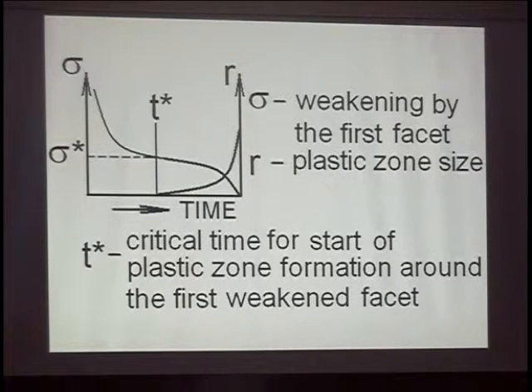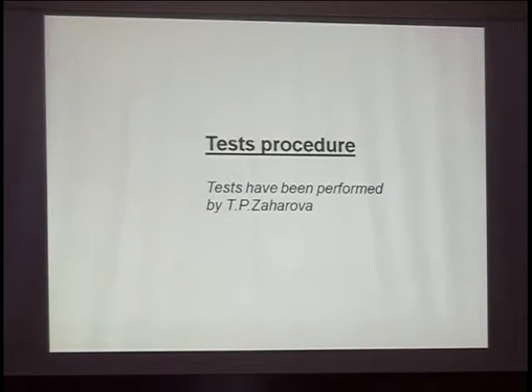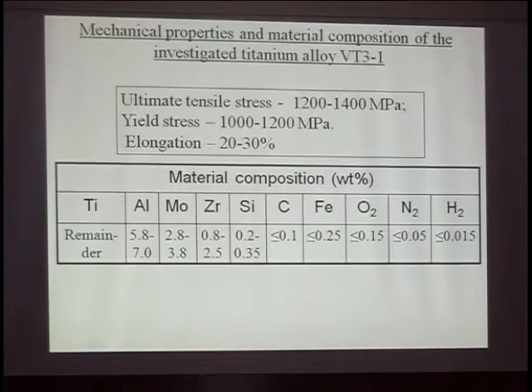To see this manner of material cracking, we performed very different conditions for material state, especially for smooth and notched specimens, to analyze this possibility of material cracking. So this is the procedure for investigating different conditions that may influence this bifurcation transition from one area of material cracking, one manner as the surface, to another, subsurface.